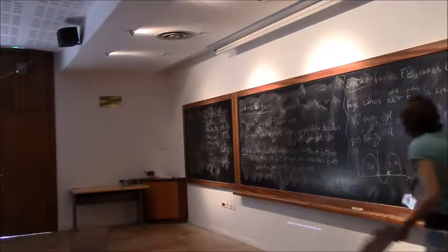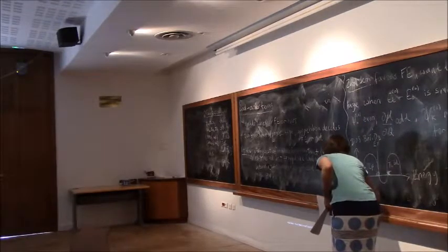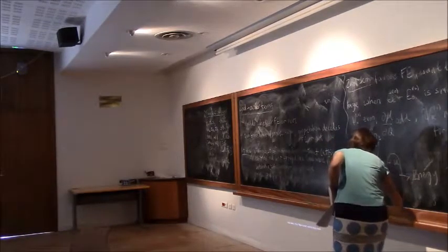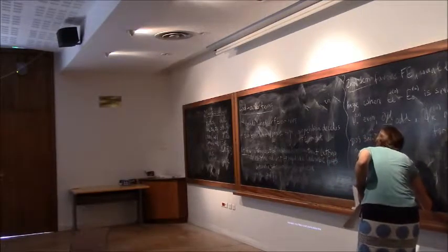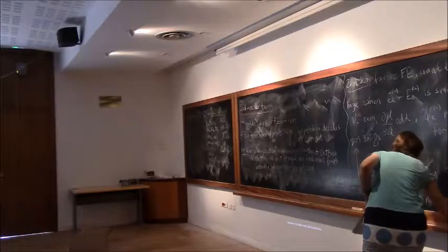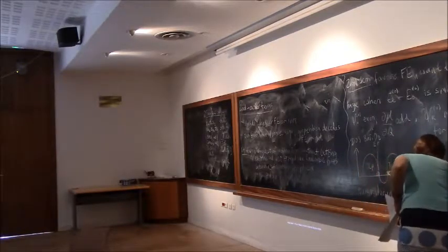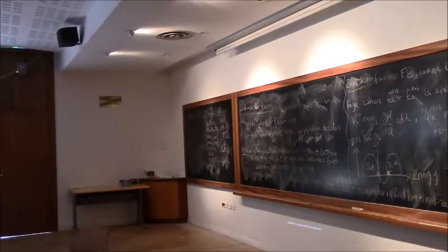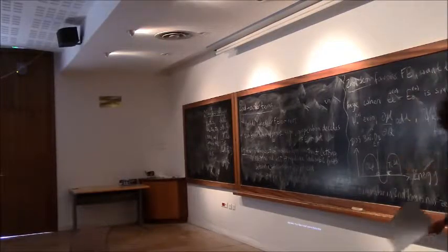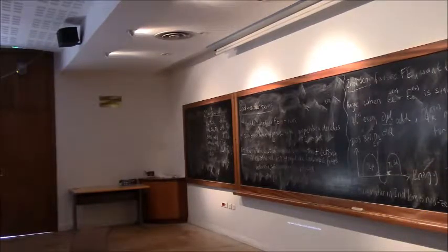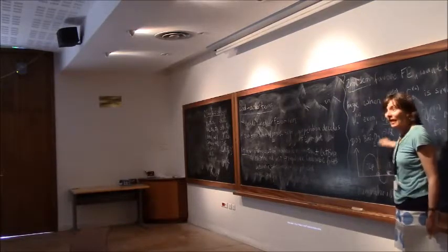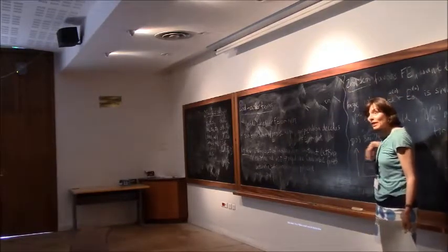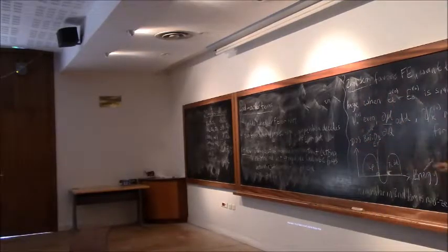So my numerator in the second term is non-zero, and the ferroelectricity wins. Or wins in quotes, because it's not really a competition. The second term is large and negative because of the d-zeroness: the conduction band has d symmetry, the valence band has p symmetry, these have different parities, and so the first excited state in this case is odd.